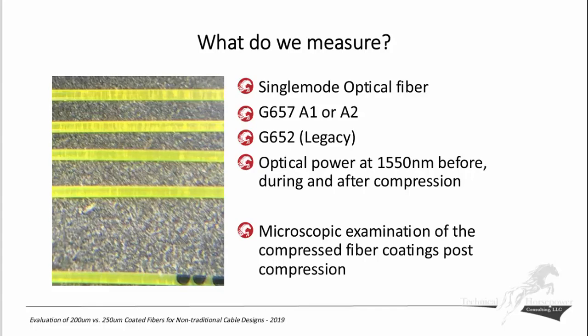And you can see on these fibers small indentations along the entire surfaces of the fibers. We were unable to identify the actual depth of the damage, but we wanted to make sure that we actually damaged the fiber in this compression. So this is a picture of the 25 micron particles. The 15 micron particles actually did not cause any damage to the coating. So beyond this stage of the process, we did not include them in the further testing. So that was one of the changes that we saw in this process. We didn't run a report on something that wasn't going to change.